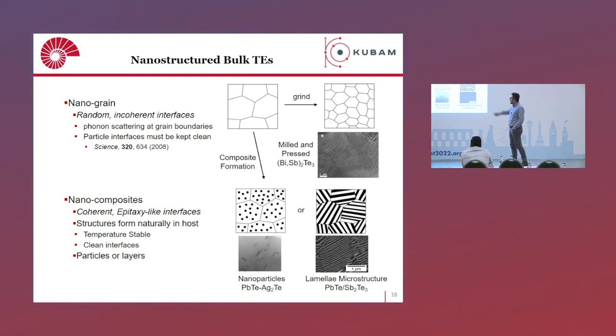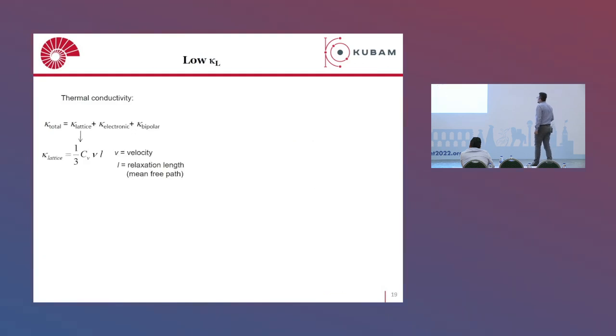So you can also create nanocomposites. Which means you can, for example, introduce intentionally some secondary phases either within the grains or at the grain boundaries, and they also act like phonon scattering centers. This is nicely shown, for example, for nanoparticles of lead telluride inside silver telluride, or by using the phase diagram of these systems, you can create such eutectic structures, and these are lamella structures of lead telluride and antimony telluride. They also have an impact on lowering the thermal conductivity.